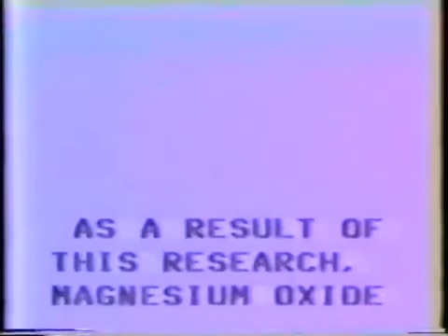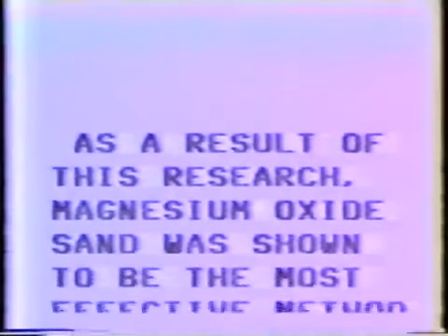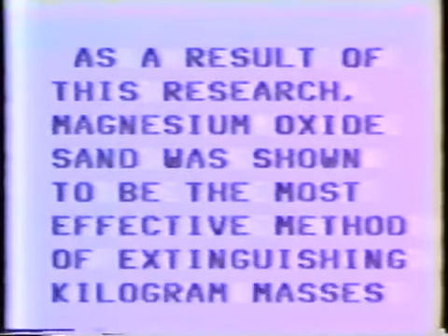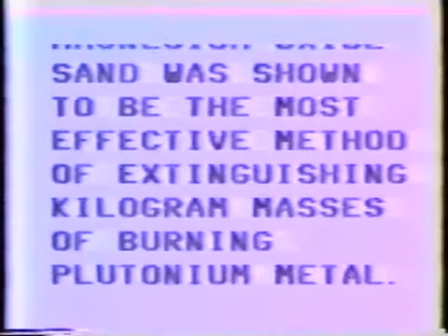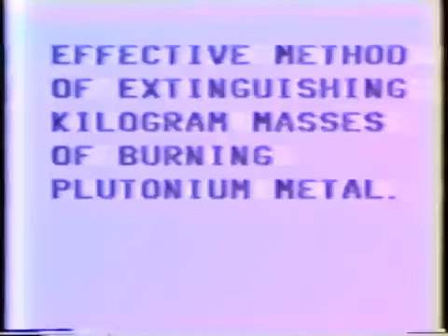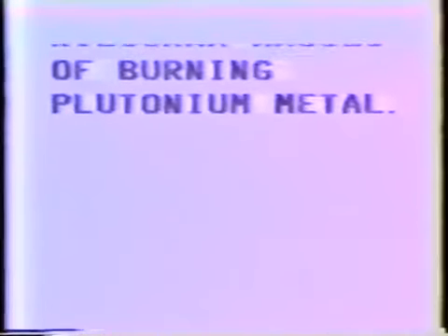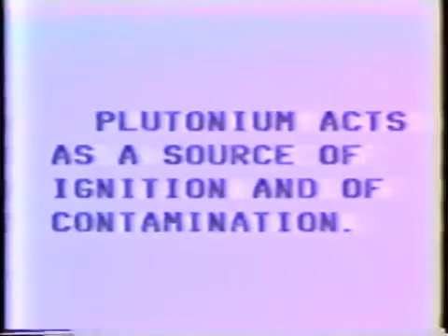In conclusion, I'd like to point out that the magnesium oxide sand indeed turned out to be the most effective way of containing the plutonium metal fire. It is not totally effective in extinguishing it. Plutonium metal will still burn underneath it, but however it provides an interesting containment so that you will prevent other materials in the glove box from igniting.